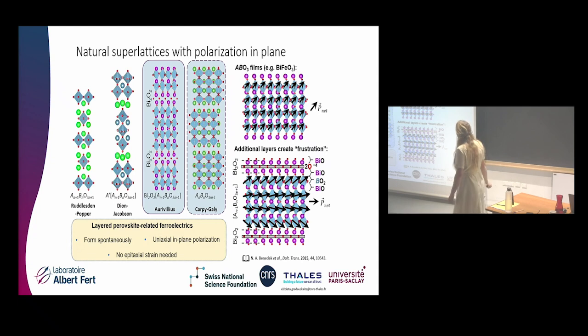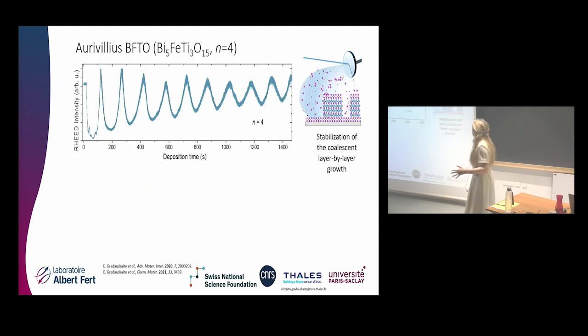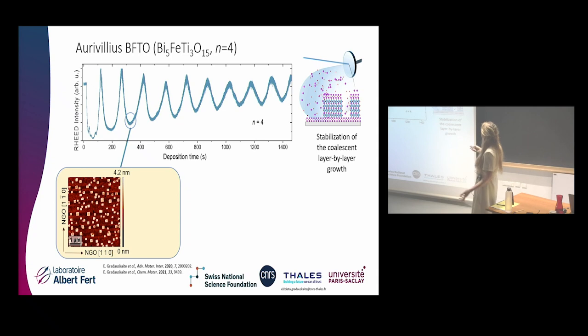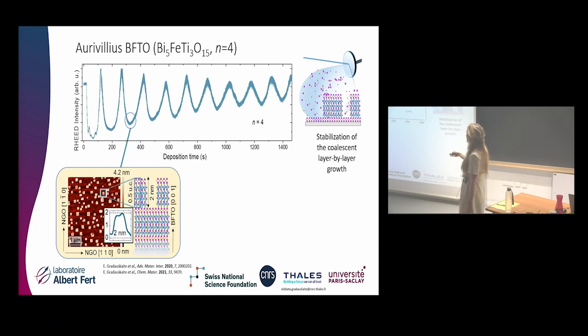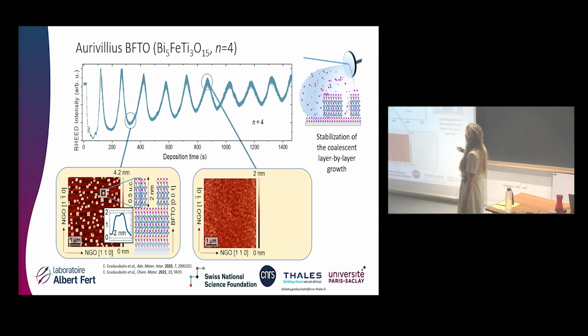And I think what was quite important with these materials is that they were for a long time seen as something very complicated to grow, only for ceramics. But in fact, with a good selection of the substrate and growth conditions, we could actually stabilize a really nice layer-by-layer growth mode in the PLD, pulsed laser deposition, where we have these minima of reflection high-energy electron diffraction intensity that we use to probe the growth. That's where we have very rough films, where actually we have these islands of exactly half unit cell in height. And then when we have the high intensity, that's where our films become uniformly flat.